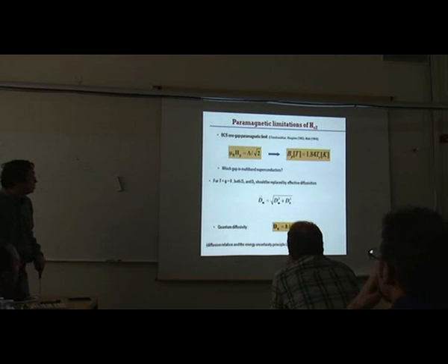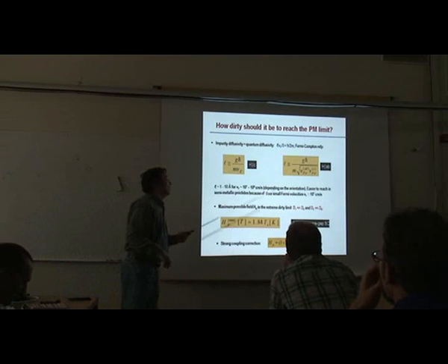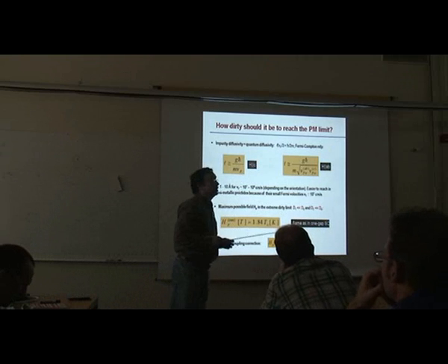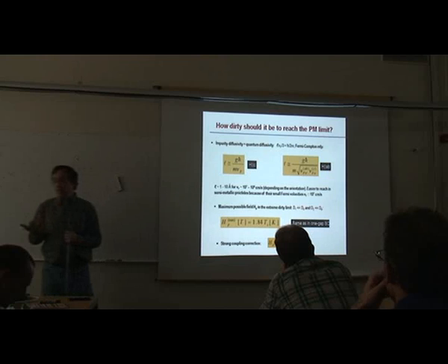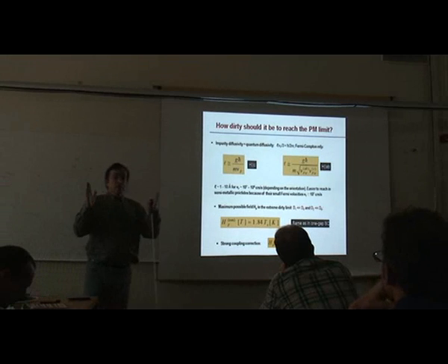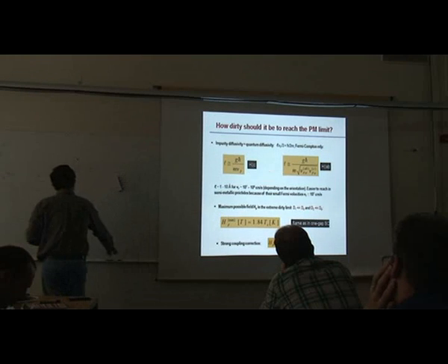Okay, so here is a little more about the paramagnetic limit. I think I should speed up a little. The question is always, what does it take to reach the paramagnetic limit? Well, the simplest way would be to add impurities, because as we add impurities, the coherence length becomes smaller and smaller, so HC2 goes up and up and up. And then, if we calculate HC2 from orbital limiting, it may be higher than the Zeeman field.